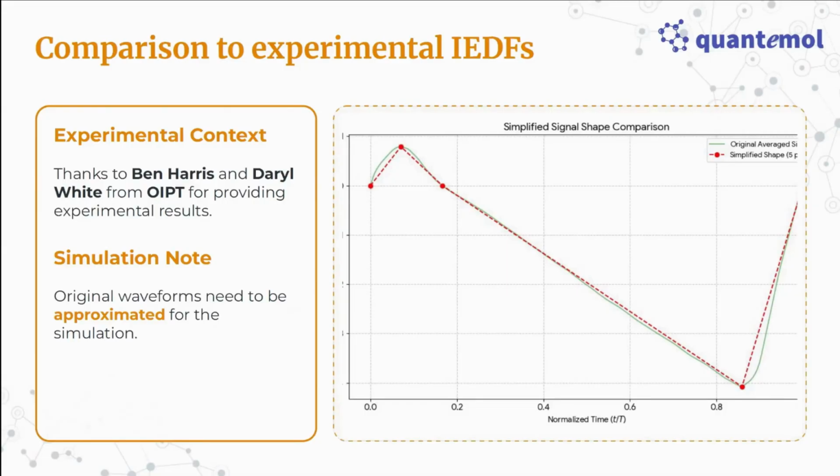Luckily they were so nice and put a voltage probe in the generator, so they actually measured the signal that comes out of the RF generator. You see in green the original, averaged over hundreds of cycles, and it's actually not as perfect as we assumed. It's not that far away. I think the major difference is that the positive phase isn't constant, but more shaped like a sinusoidal half cycle. But we did approximate it again with this simplified shape where we define these 5 points.